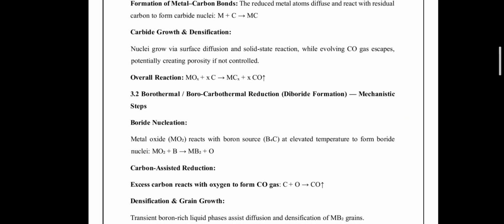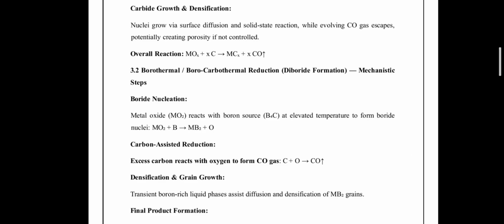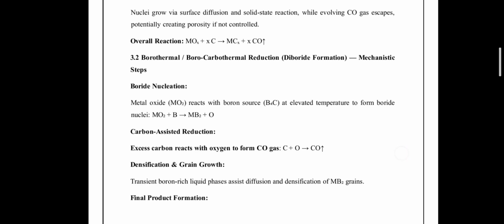Next is the borothermal pathway for the formation of diborides. Metal diborides are commonly synthesized via borothermal or borocarbothermal reduction, typically using boron carbide as a boron source. Initially, the metal oxide reacts with the boron to form diboride nuclei, while oxygen is liberated from the oxide lattice. Because boron alone is insufficient to fully remove oxygen, excess carbon plays a critical role in that case, and the oxygen is removed as carbon monoxide gas.